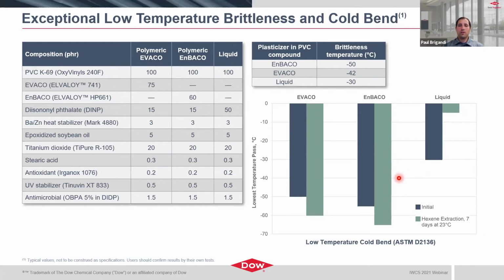Again, we've also shown here the performance after interaction with a solvent. So in this case, a hexane extraction. And what we show is, again, to the point of miscibility, the polymeric materials remain within the PVC, and low temperature performance is maintained, whereas the liquid material is drawn out, and your low brittleness temperature is significantly lower, or higher, I should say, in this case.